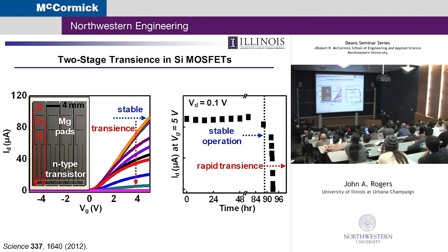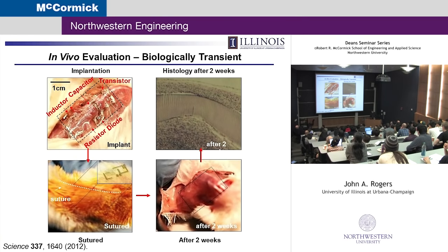So if you think about a transient electronic device, you might ask, it has a certain operational characteristic. You put in biofluids, it starts dissolving. Doesn't that change the operation instantly? You start dissolving the materials. And that is true, but that's not the way you deploy these things. You deploy them with an encapsulation layer on top. The disappearance of that encapsulation layer then defines the functional lifetime. Once the encapsulation is gone, then the water starts to dissolve the actives themselves. That changes the operation. So by adding an encapsulation layer, controlling its thickness, its dissolution time, you can achieve two-stage kinetics, stable operation, and then rapid transients immediately after that. And that's a critical design aspect.